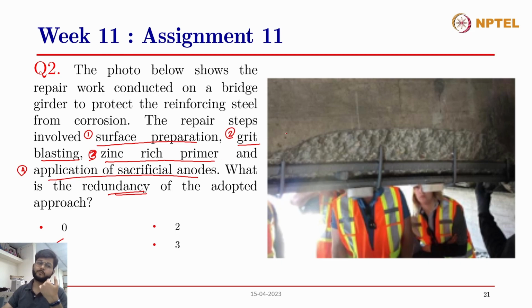Yes, so as he has rightly mentioned, surface preparation has to be done in any kind of repair technique that you are adopting. The surface has to be prepared well, cleaned and free from any debris or dust, so that whenever we are carrying out a repair work, the repair material and the substrate concrete develop a good bond. So this is a prerequisite. Then there is grit blasting. Applying grit blasting before applying a primer will ensure a good bond between the primer and the substrate concrete, and therefore grit blasting is applied to develop a good bond. So this is again a requisite technique.